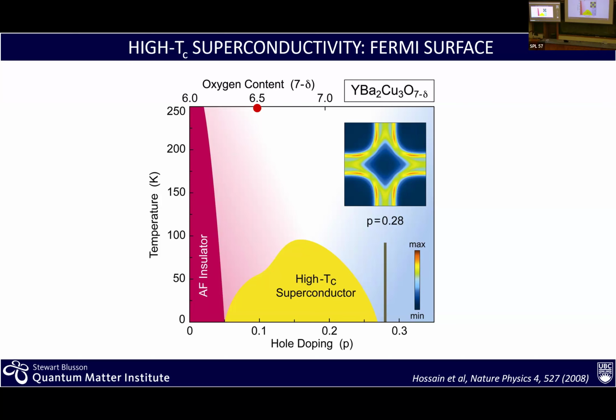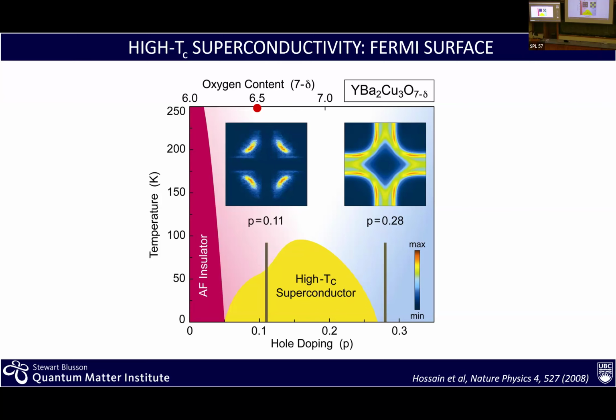And okay, this is what the conventional picture tells us about it. The Cooper pairs giving rise to superconductivity are coming out of those electrons along the Fermi surface. And as you move down towards the underdoped side, the Fermi surface breaks down into disconnected arcs. They are called Fermi arcs. And so that's really the transition from conventional behavior into unconventional behavior. And it's that interplay that we believe gives rise to the high temperature superconductivity.